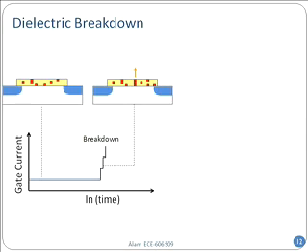So you can realize that over a period of time, bonds will be broken and defects will be formed. When a certain amount of defects have been formed, these defects, which are shown here in little red boxes, might line up. And if they line up, then you have a short circuit between the substrate and the gate, and the electrons will simply flow out. Your MOSFET is gone, no longer a MOSFET, maybe a very bad bipolar transistor with a base contact.